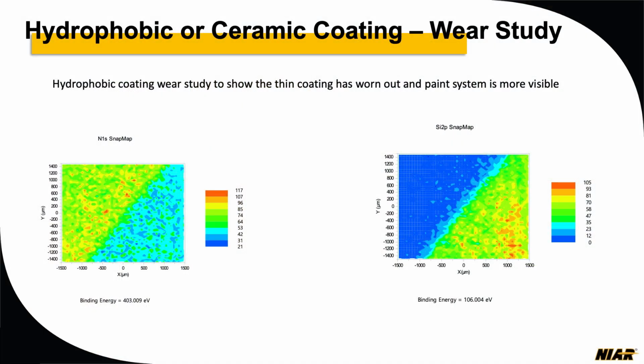Now another interesting test we did was hydrophobic coating or ceramic coating. A lot of people in industry say, oh, we got a ceramic coating and it's a very good coating where we don't have any dust stick to it or the water doesn't stick to it and it protects pretty well. Yes, but how long does it last? That's one of the biggest questions that everybody is asking. And that's why the aircraft industry is very cautious of putting it on the aircraft, because if they put it on an aircraft, will it last for, let's say, 300 flight hours?